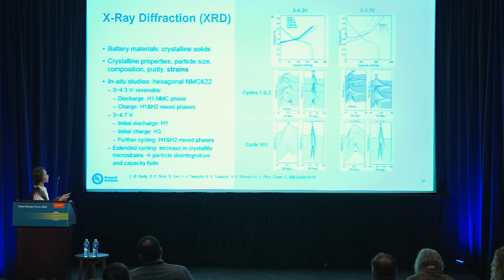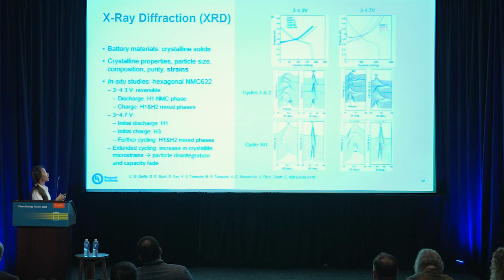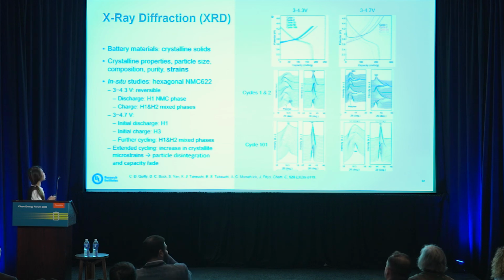On the right here, this is an example of an in situ study on hexagonal NMC622. In this study, they wanted to look at how the material is cycling beyond 100 cycles, and they did it within 2 voltage ranges, from 3 to 4.3 volts and then 3 to 4.7 volts. When we're looking at the lower voltage range, it starts with an H1 NMC phase, but on charge, it goes into H1, H2 mixed phases, as you can see here. And this is reversible, not just in the first 2 cycles, but also up to beyond 100 cycles.